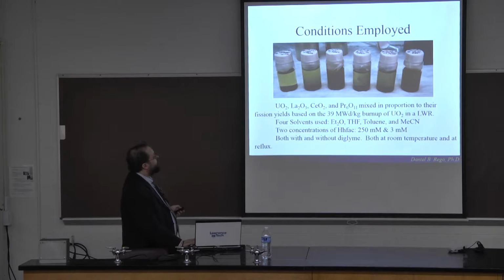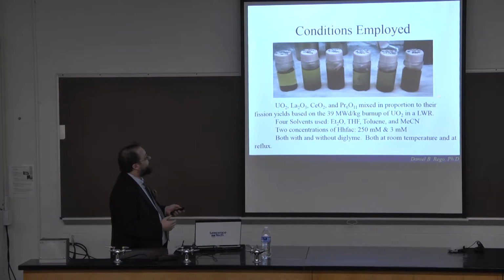So basically all I did is I took a mixture of uranium oxides and lanthanide oxides, in this case a trivalent oxide, a tetravalent, and a mixed valent oxide, and mixed them in proportion to their fission yields from the reactor. In this case, it was about a 50-to-1 ratio of uranium to the lanthanides.